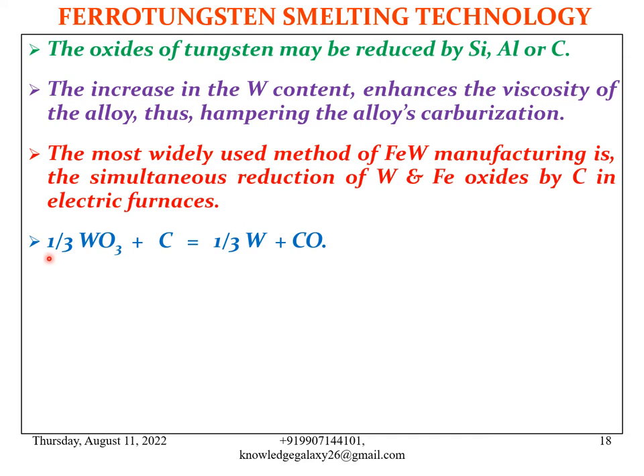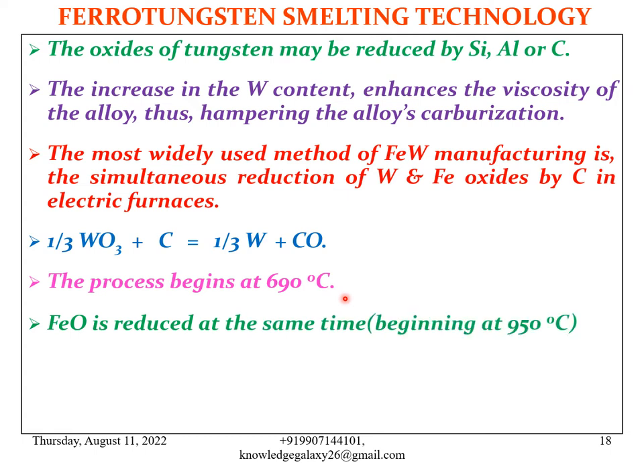The chemical equation for the reaction is 1/3 WO3 + C gives 1/3 W + CO. This is the basic chemical equation depicting the reaction of tungsten trioxide with carbon. The process begins at 690 degrees Celsius. FeO is reduced at the same time, beginning at 950 degrees Celsius. The chemical equation is FeO + C = Fe + CO.